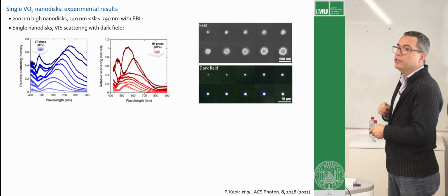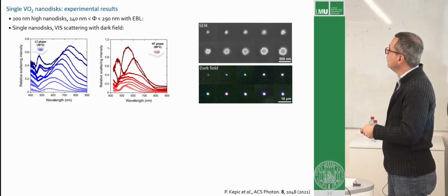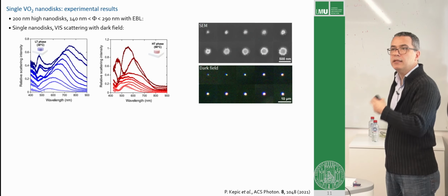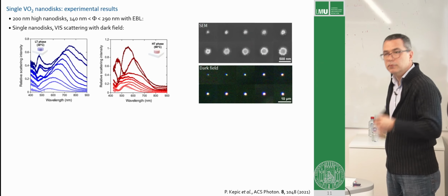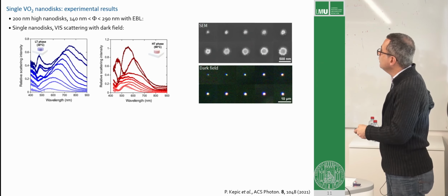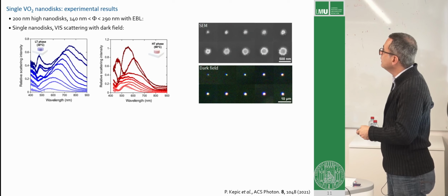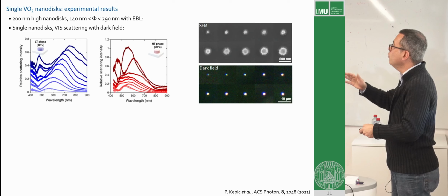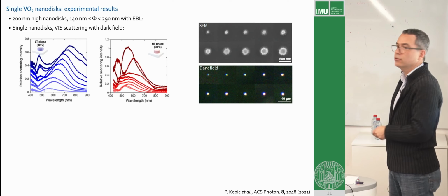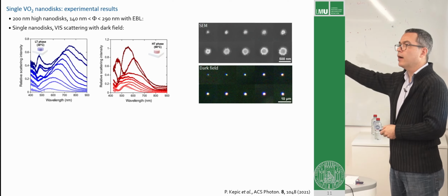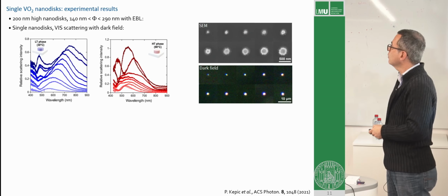And you see here the dark field images. From the smallest disk, you see here a little bit bluish, right? This is what we see in the microscope. If you look at it, it's a little bit bluish. And in fact, you see here that the smallest disks peak, the scattering peaks here close to the bluish greenish, 500 nanometers or so, 510. This is a turquoise color.